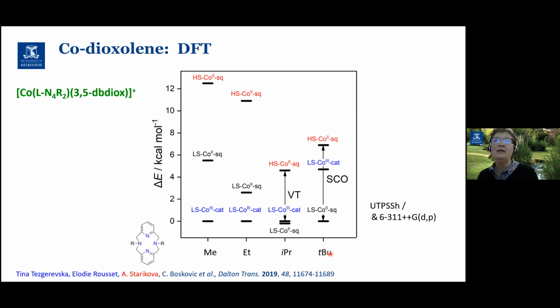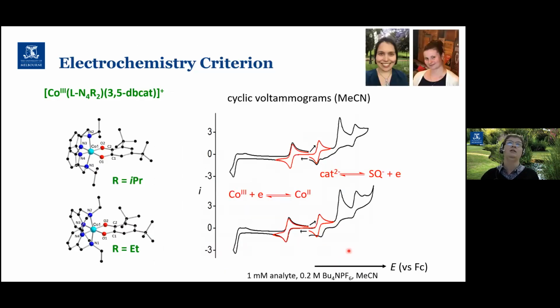But then when you go all the way to the tert-butyl group, now the low spin cobalt-2 semiquinone form has been stabilized so much that that really is the ground state. And then the high spin cobalt-2 semiquinone has come down enough in energy that you can actually access that spin crossover transition that Hans-Jörg Krüger and his co-workers saw. So a couple of things here. First of all, these DFT calculations are really powerful, and really nicely consistent with our experimental data. And again, emphasizing that very small changes to those ancillary non-redox active ligands are really influencing the charge distribution and whether you actually see a VT or a spin crossover transition.